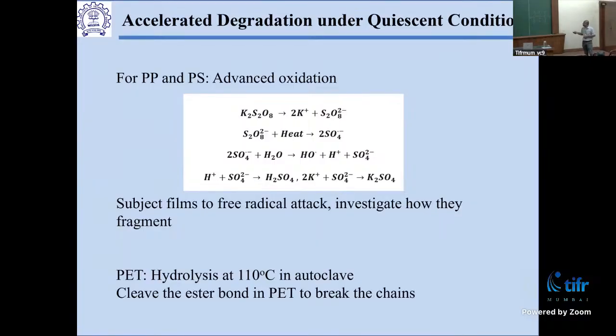We take a potassium persulfate aqueous solution, and if you heat it up, it dissociates to give you all these radicals. The alternative to this was something called a piranha etch, right? There's actually something in chemistry where you can take a solution with peroxide and acid, and if you heat it up, it gives you what's called a piranha solution because it just chews up everything you put inside.